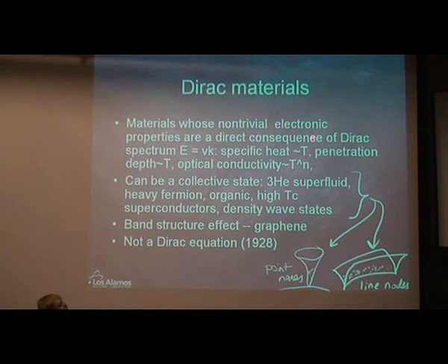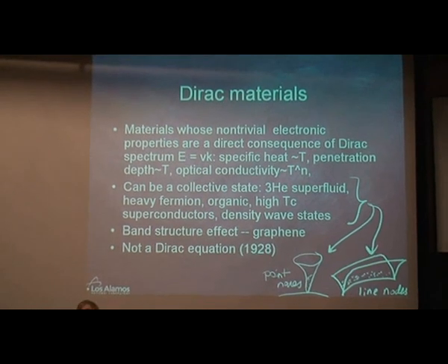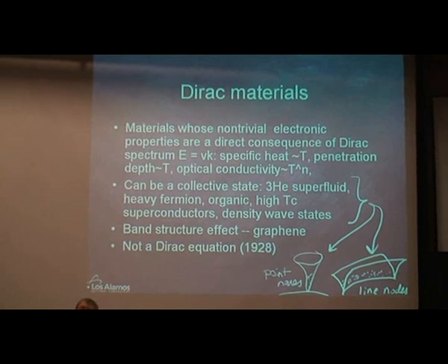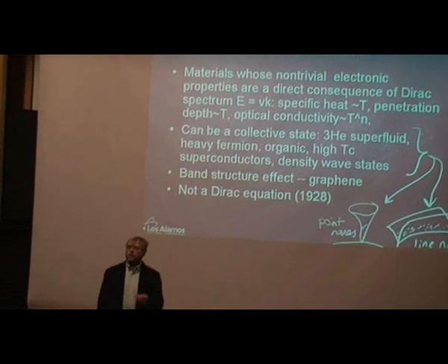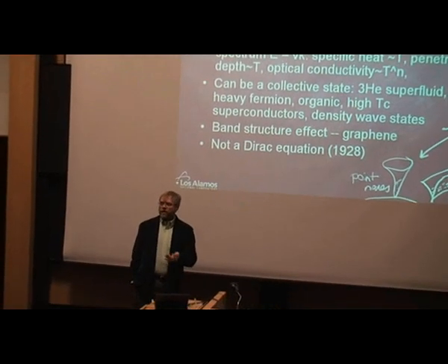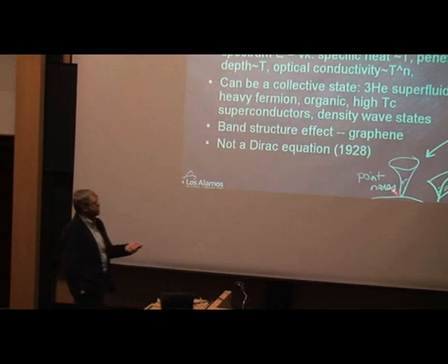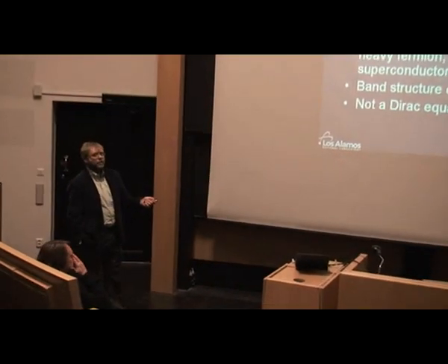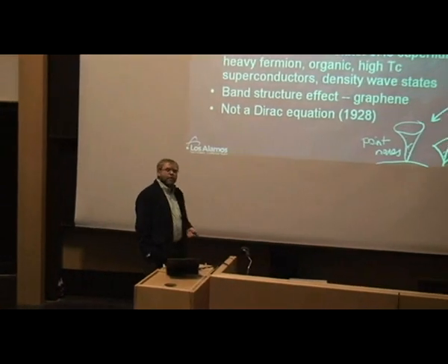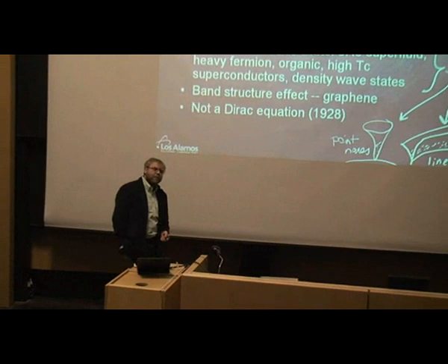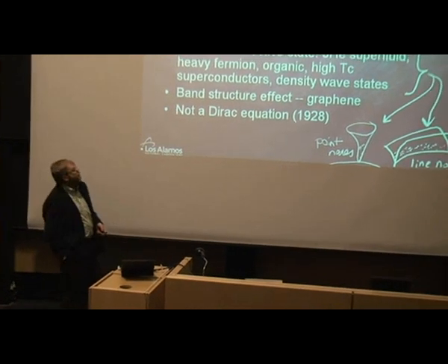They are responsible, for instance, for unusual power law dependencies of the penetration depth, specific heat, and other responses of the superconductors, in a very different fashion from what you expect from conventional superconductors. People sometimes call these excitations the nodal fermions, but they also have this Dirac-like spectrum, energy linear in momentum. Essentially, it's like an extreme case of the Fermi surface. The available phase space for excitations at lowest energies shrinks to zero. So it's not exactly a gap, but it's not exactly a standard metallic situation.